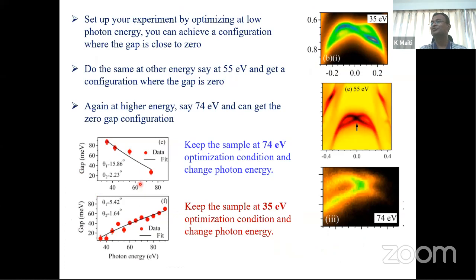Now, when you are doing it at Elettra, we optimized at 74 eV. We found the Dirac cone and then reduced the photon energy, and we see that as we go away from this optimized point, the gap opens up. Okay, so this is the opposite scenario. So this is summarized here. Whenever you optimize the sample position, you are able to get the Dirac cone without any gap, at 55, 35, 74 eV. If you keep the sample at that position and change the photon energy, you see that there is a gap at other photon energies.